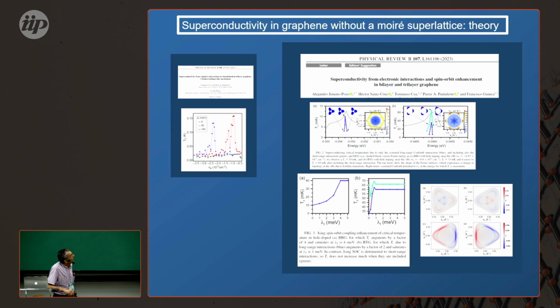We did the calculation and we found superconductivity, but at a much lower critical temperature. The superconductivity was different—this is nodal superconductivity, in the sense that besides having different signs in different valleys, the order parameter has nodes within each valley. We found that it was enhanced if you added some Ising spin-orbit coupling.